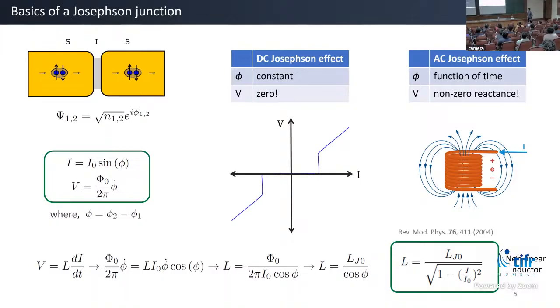Yeah, good question. One thing we see is that when we make the Josephson junction and the superconducting contact, that contact can sometimes be not so transparent, and you won't see a superconducting state, like zero resistance. That is one of the major problems, and for that we use different strategies. For example, we do in situ cleaning inside the sputtering chamber. We do some vacuum annealing after the device is made, but even with that, sometimes the transparency is not so good and the device doesn't go to zero resistance. That is one factor. Other than that, the device is reproducible. If the junction works, it is also quite stable, because we are using a local backgate that gives a quite clean response compared to other people who have used a global or top metal gate.